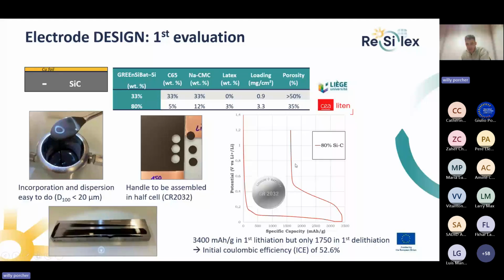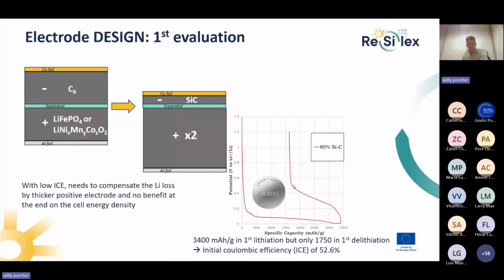However, we are able to put a lot of lithium inside the material, but only half of the lithium can be removed. It's not very nice for assembling high energy density cells. To explain it, with this electrode we significantly reduce the anode thickness, but we need to compensate for this lithium loss. We talk about initial Coulombic efficiency, which is the ratio of what you can remove compared to what you put in the material.